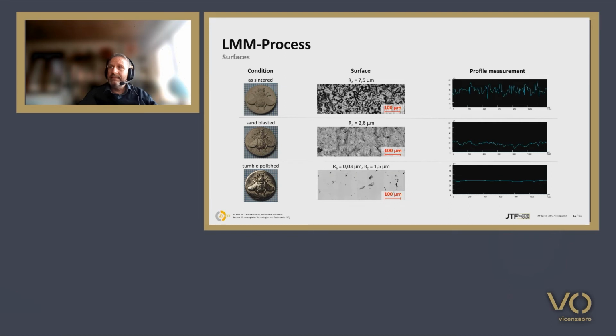So as sintered, meaning as printed and sintered, we have a surface Ra of about 7.5 micron. You see on the right side a profile measurement. And if you look at it with a very high magnification, you really see the printing pixels. Currently we are using a 4K projector, but we're now going to higher resolutions. So this will get better over time.